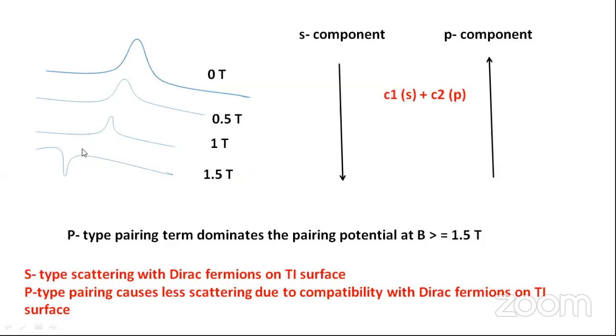So the amplitude is decreasing and then there is an inversion from spike to dip at around 1.5 Tesla. We try to explain this based on the competition between the S-type component and the P-type component in the pairing. We know that as magnetic field increases, there is a decrease in S-type pairing strength, and an increase in the P-type pairing strength. And we also know that P-type superconducting pairing is more compatible with the Dirac electrons of a topological insulator surface states, which is why they are proposed to host P-type superconductivity when in proximity with S-type superconductors.